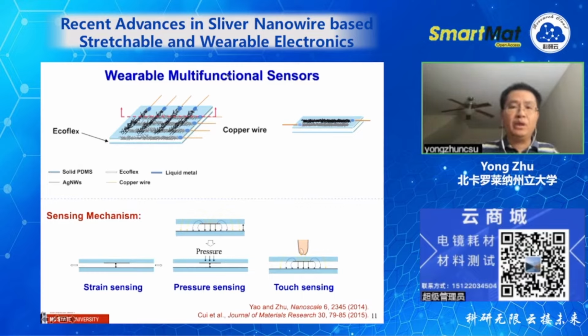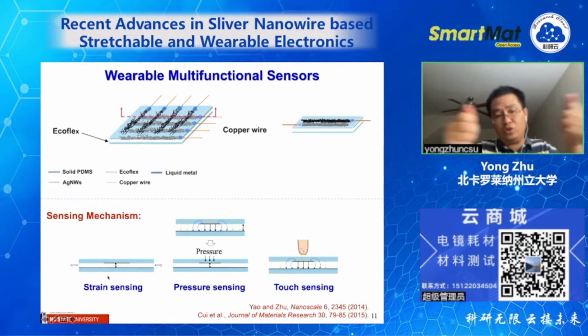So the first one is a wearable multifunctional sensor. This is a multiplexing sensor array, but the mechanism is quite simple. Essentially, it's a capacitor. We have two electrodes. We use silver nanowire as the top and bottom electrodes, and then you put a dielectric material in between. As a strain sensor, when you stretch it, the overlap area increases